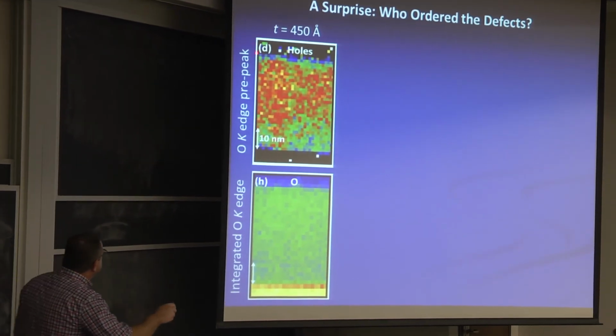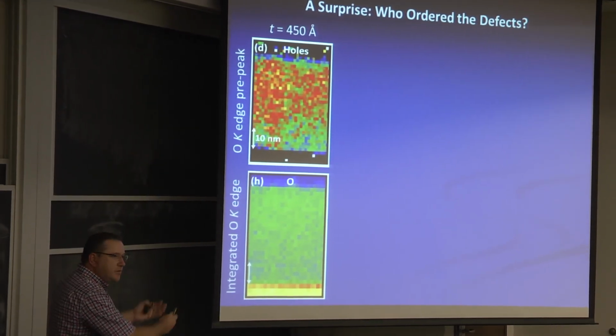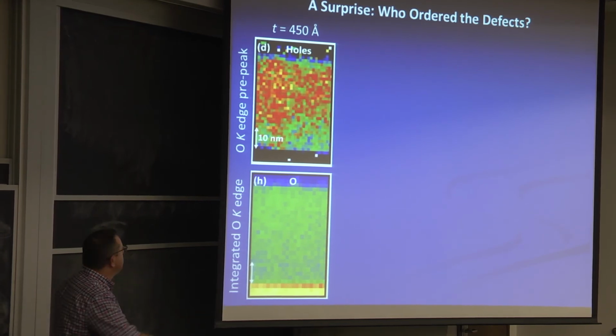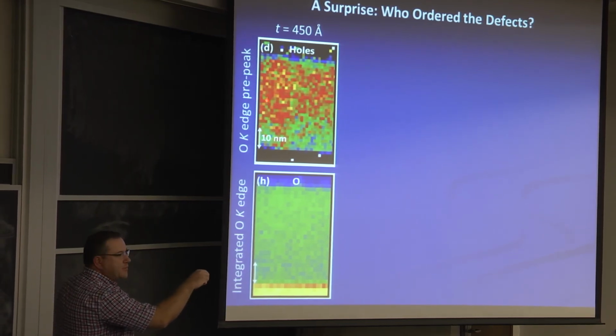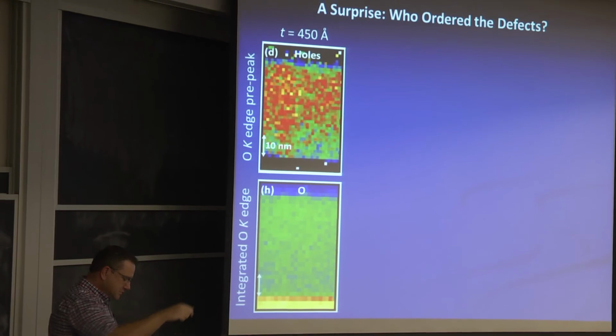So this is not just looking with electron microscopy. The structure was perfect practically every time. We're looking here with the spectroscopy part, and we're mapping the holes. If you remember from MATS 3011, you grab an electron from the valence band, put it up to the conduction band, you leave this mysterious thing behind, which is like a positive charge that moves around, right? That's a hole. Our material happens to be a hole conductor, and we had a way spectroscopically to map the density of holes as a function of position.